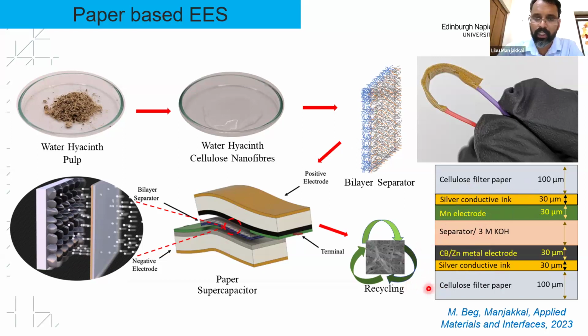One of the major achievements of this work is that in battery or energy storage device fabrication, Celgard is one of the best polymer based separators reported, but we found some issues with the Celgard based electrode in flexible applications, especially high impedance. To overcome that, we made a cellulose based bilayer separator using cellulose nanofibers, integrated it here, and now we are improving its performance. If you would like more information about this sensor, you can contact me after this meeting and we can have a chat about this work.